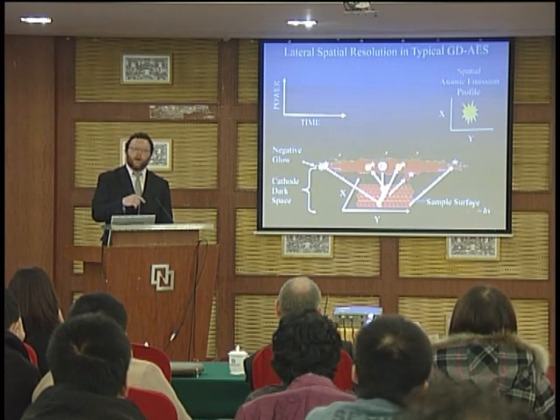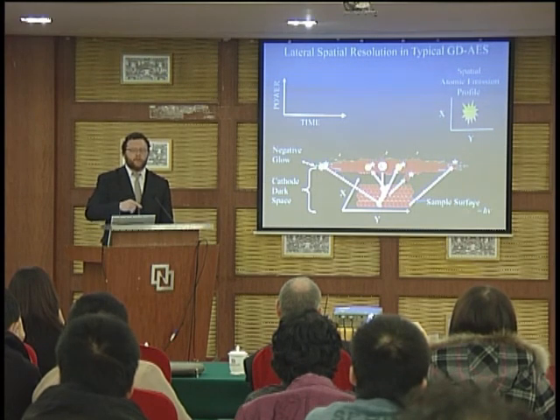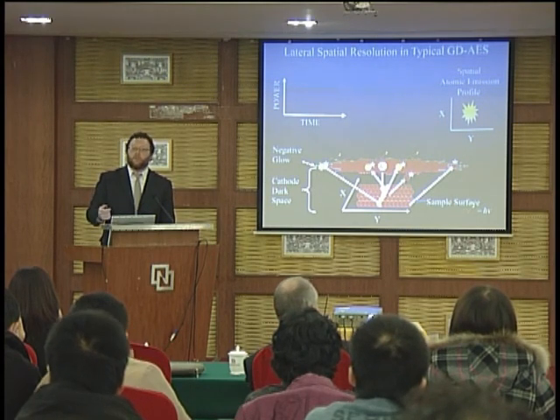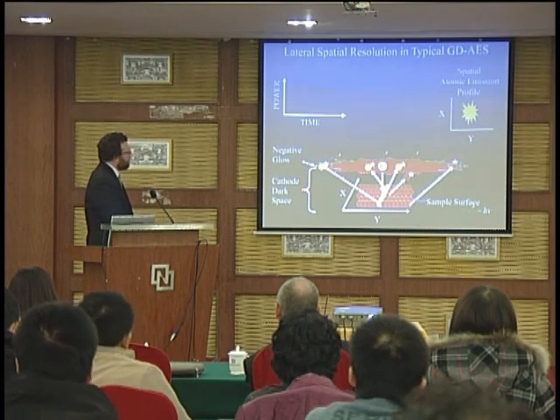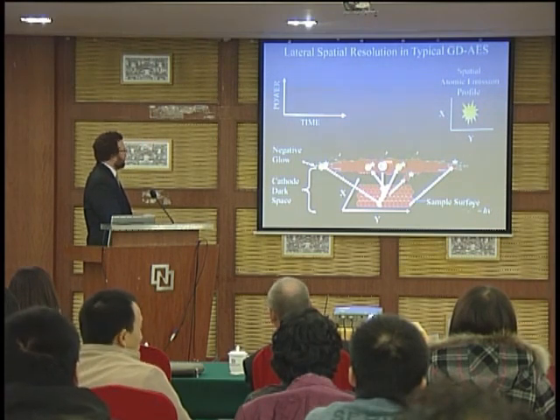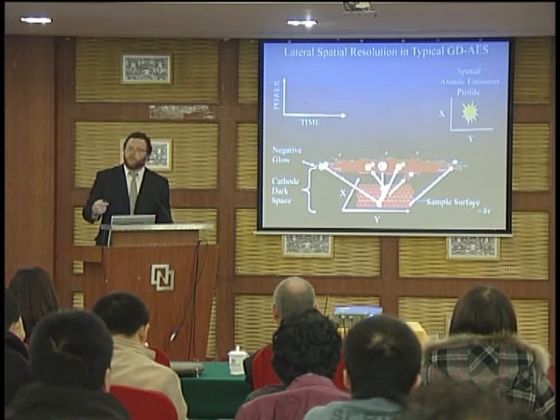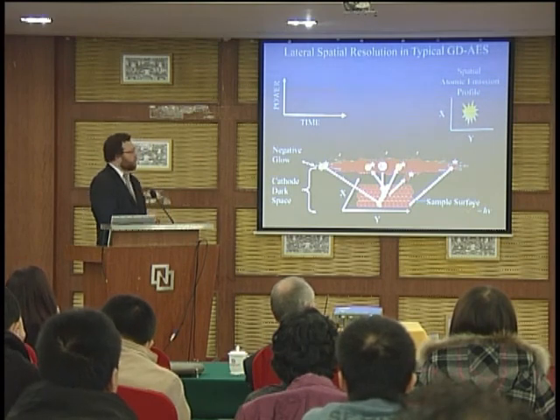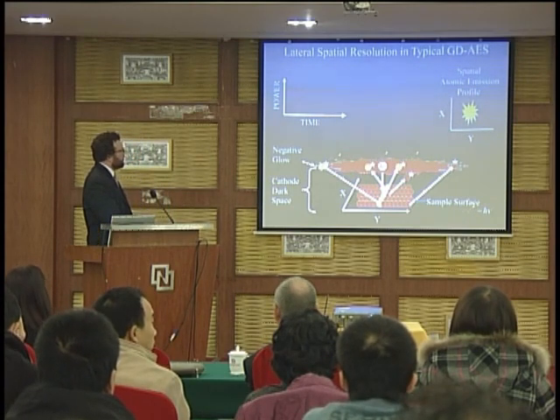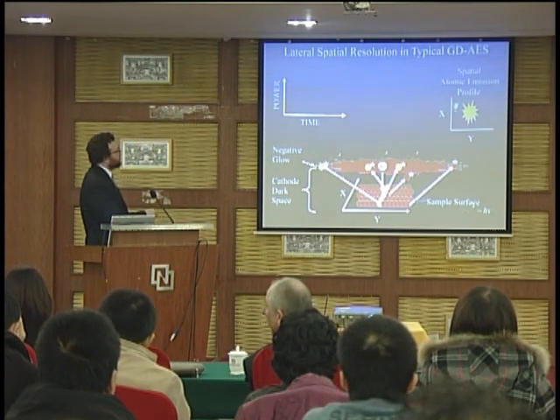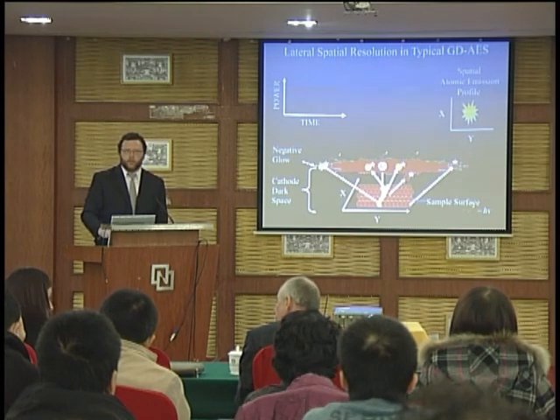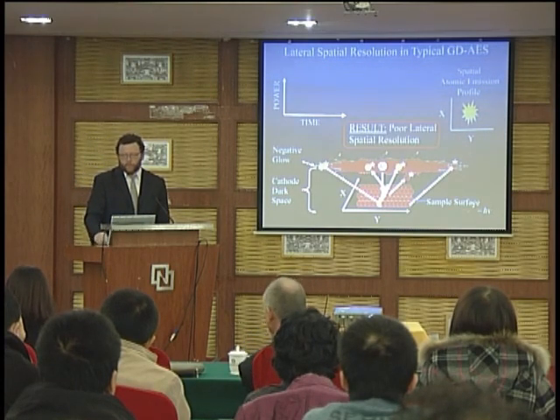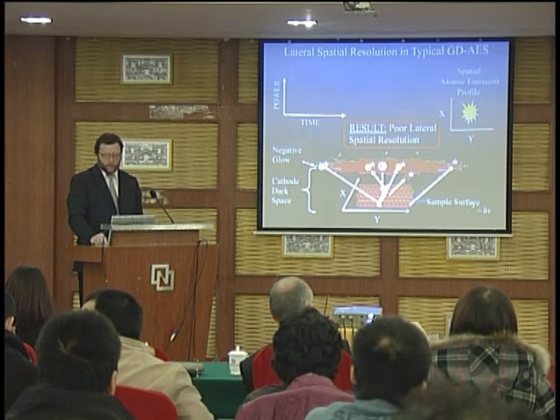But you think about the problem here, in getting lateral spatial resolution, and it has everything to do with diffusion. As those atoms move from the surface, they bounce along within the negative glow, they're excited multiple times, and so what you get, if you were to look at the selected wavelength of the emission for your yellow atoms here, is a big blob. So there's very little spatial resolution. So the result, of course, is poor lateral spatial resolution.